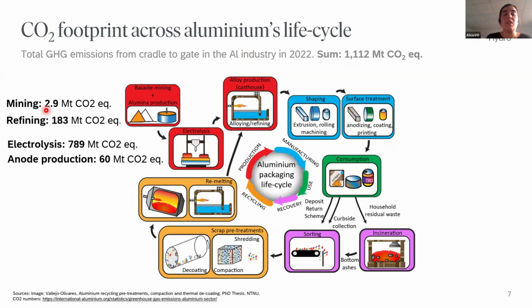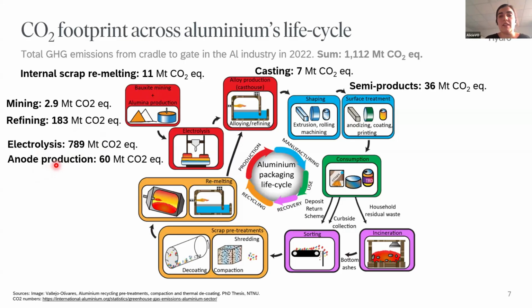mining bauxite and then refining through the Bayer process into alumina generates significant amounts of CO2 equivalent. Then reducing the alumina into aluminium is of course a very energy intensive process. The production of anodes, and then we have other processes like remelting scrap, casting, shaping the aluminium into semi-products like extrusion billets, and then finally into products, and then collecting, treating, and remelting the scrap.